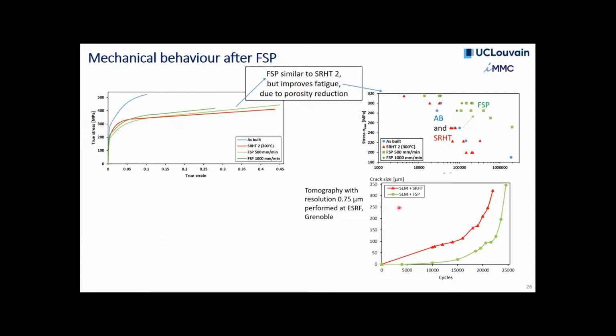So here is also an interesting result we got with these in situ tests at the ESRF, where we look at the crack length as a function of the number of cycles. And you can see here the stress relief heat treatment. The nucleation of the crack is quite early on, and we actually missed a bit of the beginning. We weren't expecting it to happen so early. And as you can see here, it's growing pretty much at the same speed as the friction stir processing material, but that actually nucleated much later.